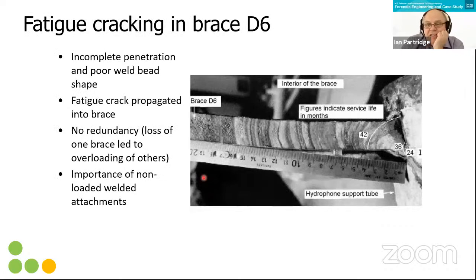This is an interesting picture because over here you can see the initiating point, then 24 months, 36 months, 42 months of operation, and then finally fast fracture. So you can see the fatigue beach marks. But what's interesting about this photograph is that it shows you that fatigue crack growth is not linear, it's exponential.